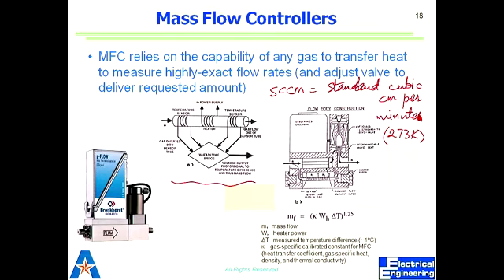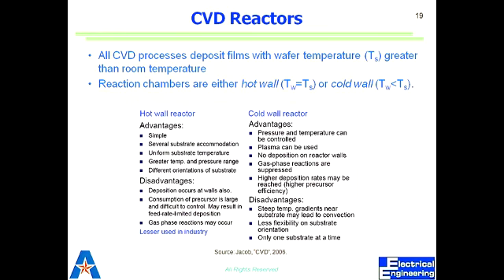the resistance value. So what we want is to maintain exact flow. Flow we define in terms of SCCM, which is standard cubic centimeter per minute. As the gas flows into the sensor and out of the sensor, we see the change in temperature after heating, and that difference tells us how fast it is flowing, because when gases flow, they lose temperature. When you know exactly how much you are heating it and you don't get that, that tells us the amount of the gas that is passing through. So that's something that we use to adjust the flow.